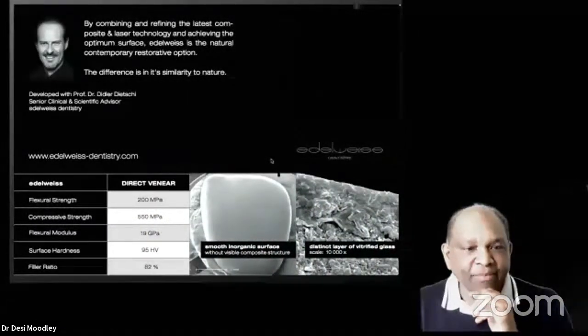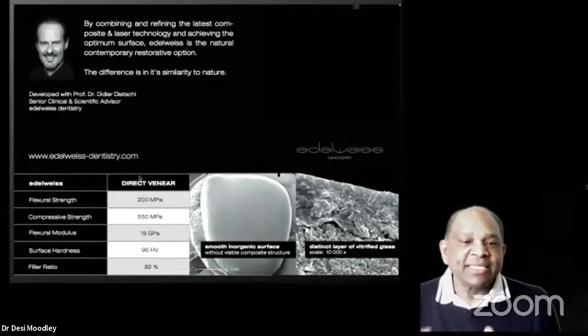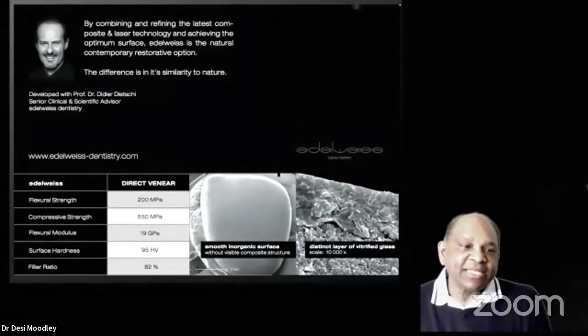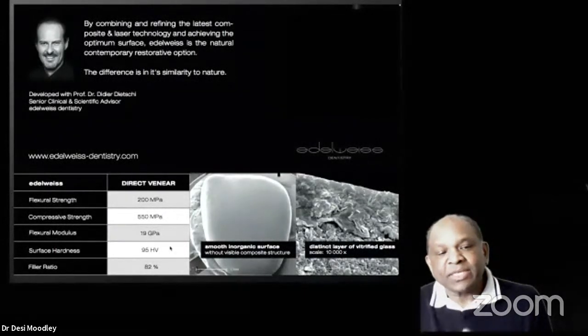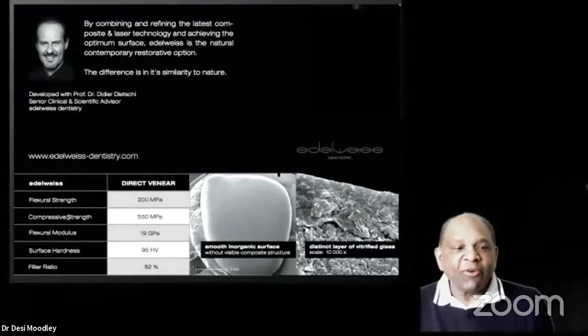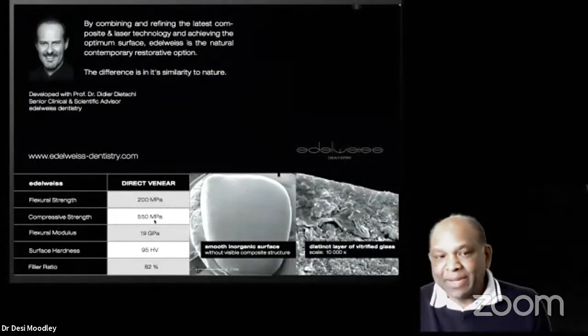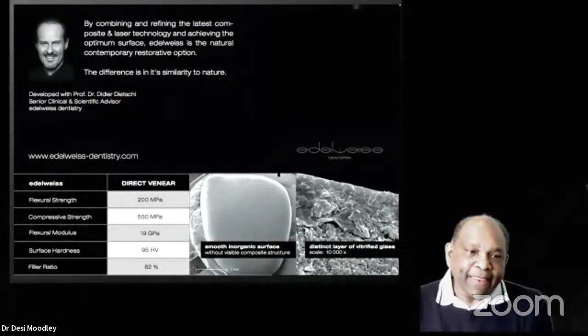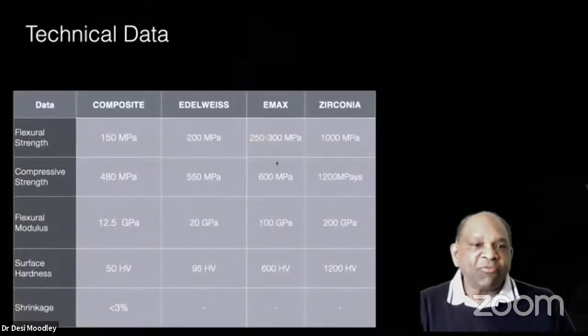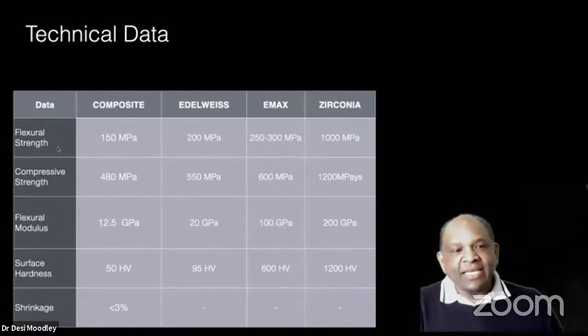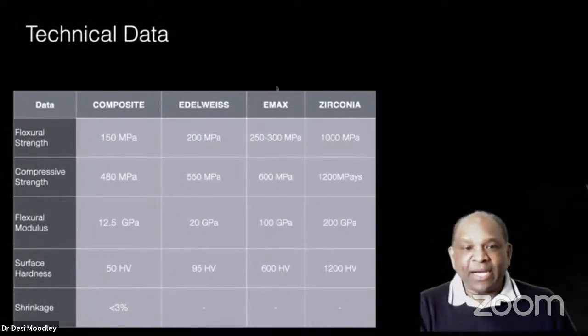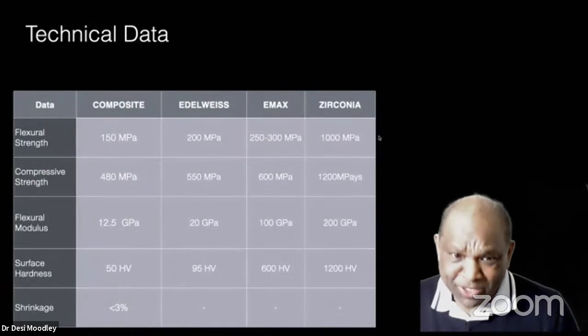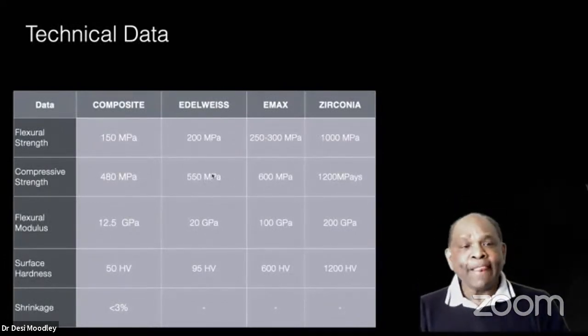This is again from University of Geneva. What it has done through this process of vitrification and laser sintering, it has moved the physical properties of the material to that close to particle filled ceramics. For example, the compressive strength is 550 megapascals. And Emax, which is lithium disilicate, is 600 megapascals. So if you compare the Edelweiss, it has taken the physical properties and upped it to very much closer to your particle filled ceramics. But you don't want to go too high compared to Zirconia, which is too strong. So the compressive strength is about 550 compared to Emax, which is 600.